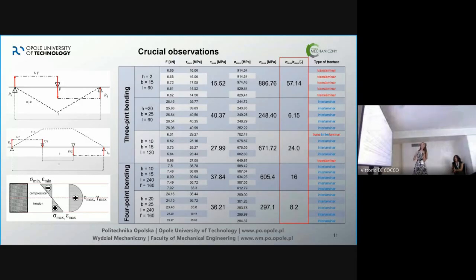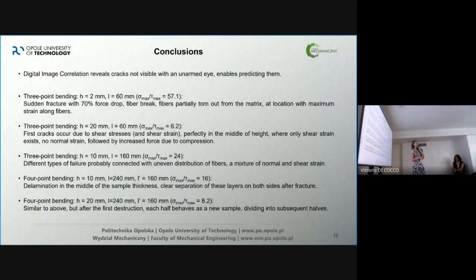Okay, so summing up to the conclusions, because the conclusions are always the most worthy. First, the most important is that the digital image correlation reveals cracks that we can't see with the naked eye. The specimens seemed totally normal, and we would think that they're going to work and work and work. But the strains using the digital image correlation showed that in a second we're going to have a crack, so it's not safe anymore. I summed up all of those specimens.